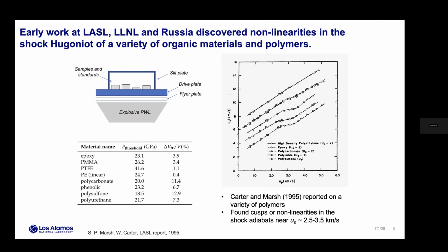They're offset in shock velocity, just for clarity. But what you'll see is that a number of them have cusps and kinks and nonlinearities associated with the material as you go up to higher pressure with the Hugoniot.